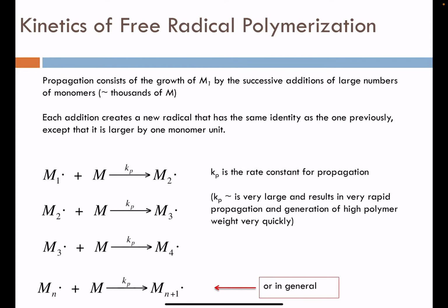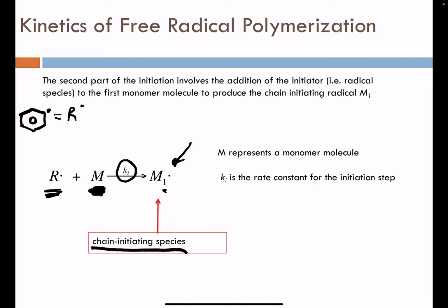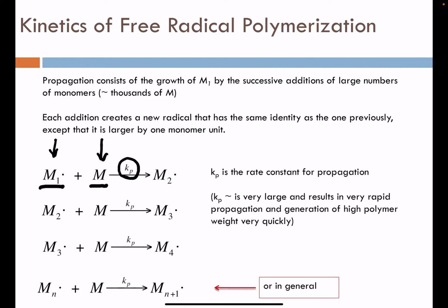Okay. So, since M1 will be required to react with yet another monomer, we can expect a pattern in the equation to look similar there. So M1 will react with a monomer. We'll see another propagation constant here, Kp. So this is technically different than the Ki because we have now a monomer-based radical reacting with free monomer, which was different than the phenyl radical reacting with monomer in the Ki example. So we still distinguish those rate constants purposefully there.